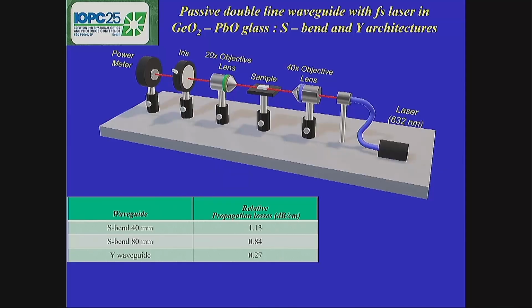By using this experimental setup, we will determine the propagation losses for all the cases, and the best result was found for the Y configuration, followed by the S-bend with 80 millimeters. I would like to highlight that these are not good numbers to be used because they limit miniaturization, but they can be used in situations where space is not a problem.